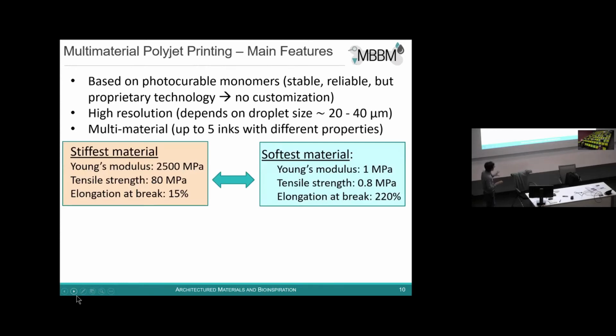The 2 basic materials, so the 2 most extreme materials that we can use, are the stiffest material, which has a Young's modulus of about 2.5 gigapascal, so it's a hard plastic with an elongation at break of 15%. And the softest material has a Young's modulus of about 1 megapascal with an elongation at break of 220%, so it's an elastomer. So we have 3 orders of magnitude variation in mechanical behavior that we can combine.